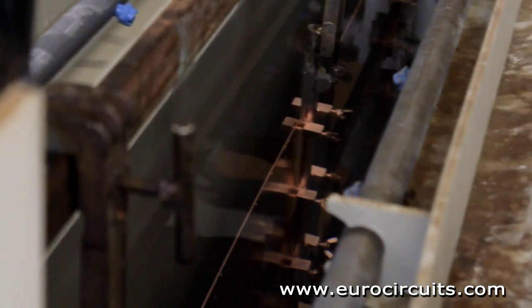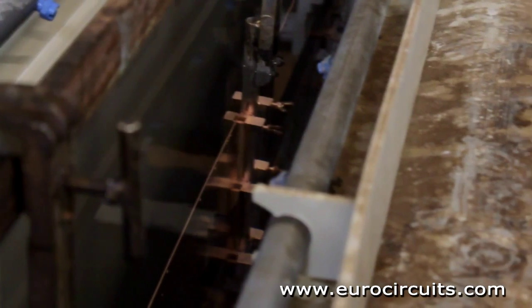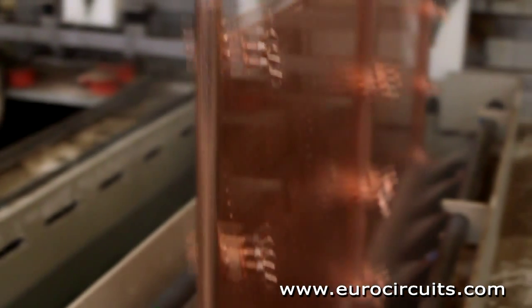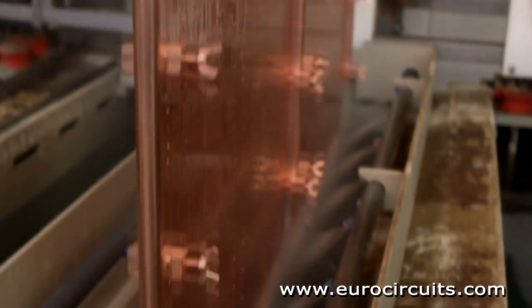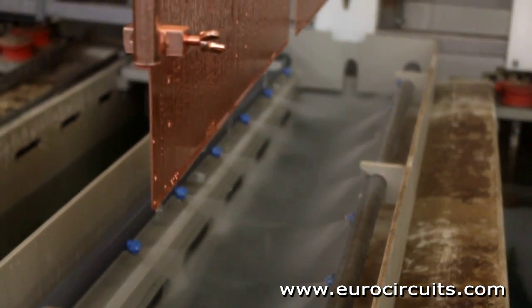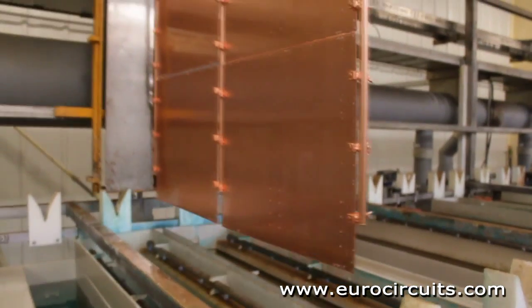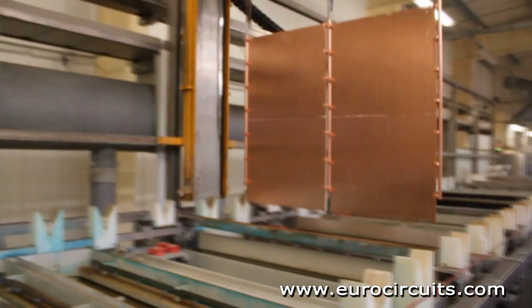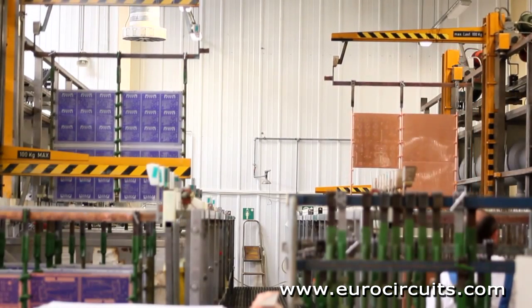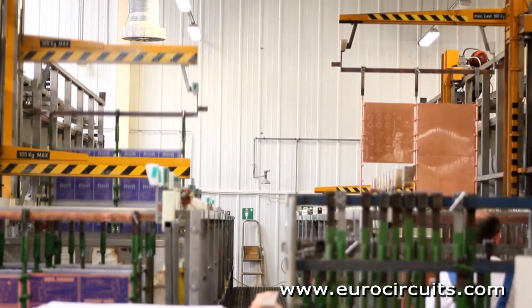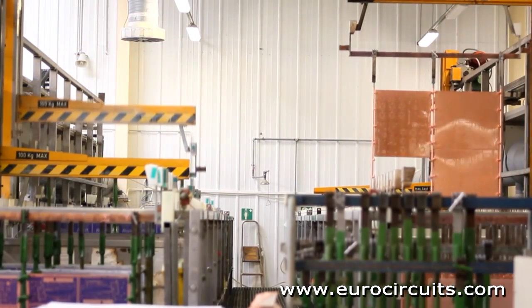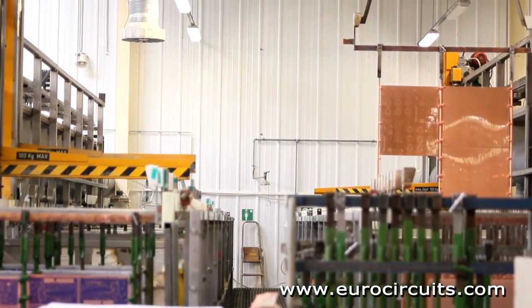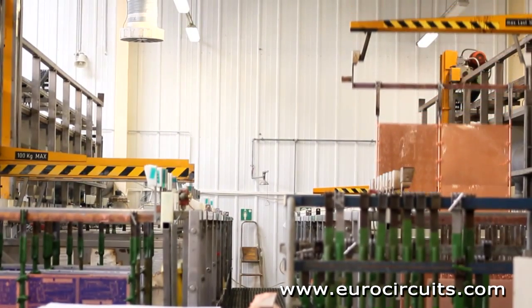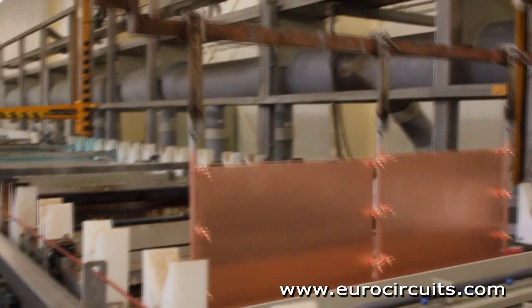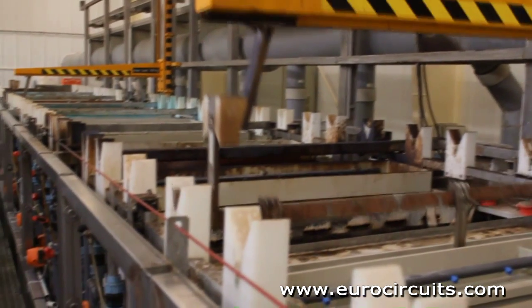This thickness must be electroplated, but the walls of the holes are non-conductive glass cloth and resin. So the first step is to deposit a conductive layer over the hole walls. We use electroless copper. That is, we deposit chemically a layer of copper about 1 micron thick over the walls of the hole, and incidentally across the whole panel. We pre-treat the panel, then we seed the whole wall with microparticles of palladium, and finally deposit the copper.